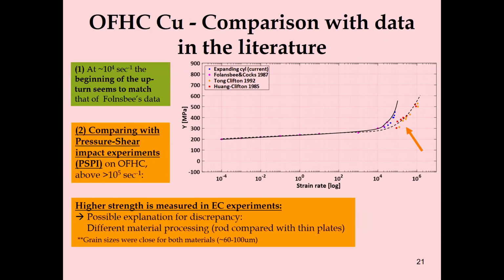And looking for additional results in the literature, we were looking at some pressure shear experiments that were done by Clifton and some students of Tong and Huang. And comparing that, we saw that our results are predicting higher strength. Looking for reasons to explain this, again, we're looking at a coupled effect when we're looking at impact experiments. But I must say here that for these experiments, we're looking at the area of 5 GPa, so the shocks are not very high, and the expected thermal softening was below. But comparing the materials, the grain sizes were almost the same, but the material processing was different. We were using a rod, and they were using thin plates, and we believe this difference was the main one showing differences, and that is seen well in copper in the literature, showing differences in strength measurements, also in quasi-static regimes.